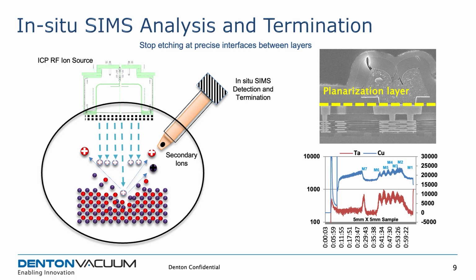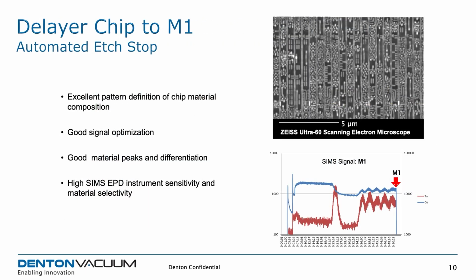So I just have a couple slides about applications we did. Here's an etching. This is not advanced node, but this is etching down to M1 and stopping and imaging. So in this case, we were able to clearly see the SIMS signal and stop on M1 based on it. And the result in the top right shows a pretty good result of M1. If you move around the chip and look very closely, you can see that there's a little bit of M2 left in patches, so it's not the perfect result.